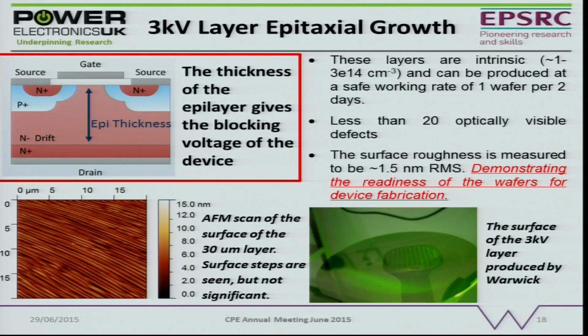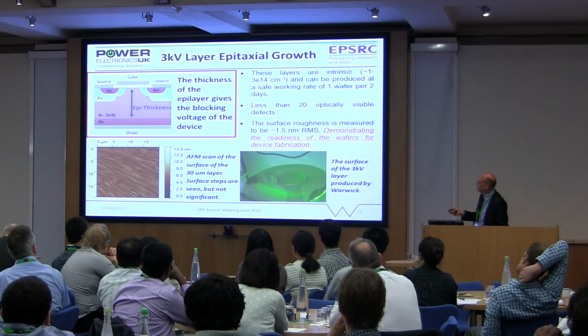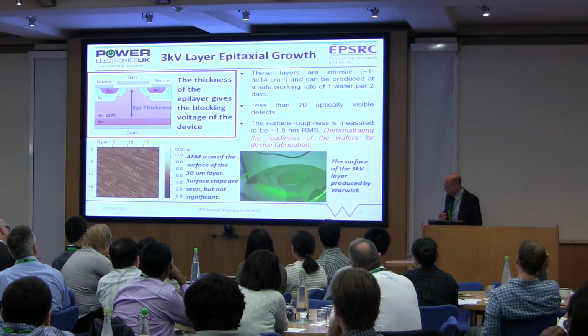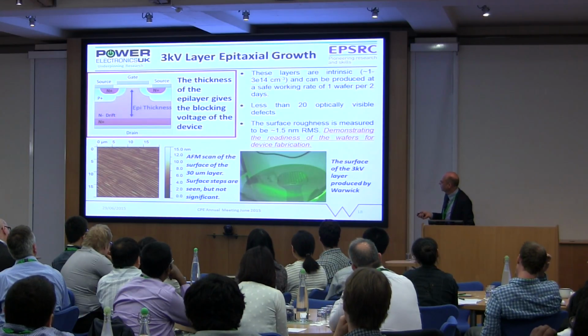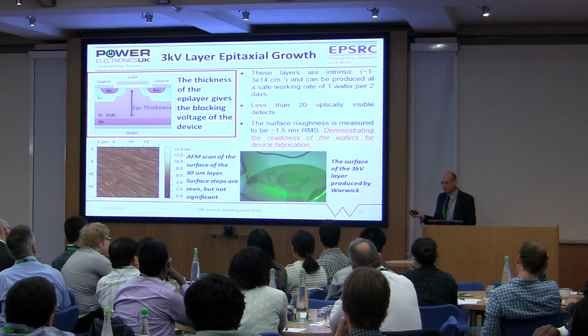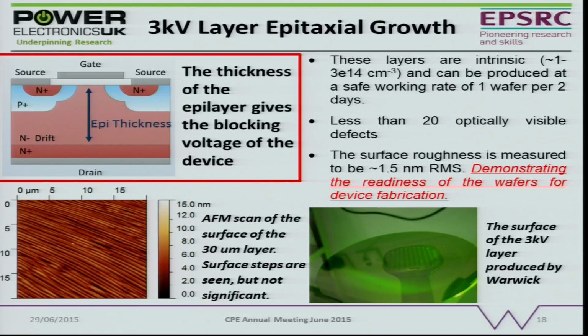So here's some of the work that's been going on in this work package. Obviously, we want to grow thick epitaxial layers. Typically, to get to 3,000 volts, you need 30 microns, and to get to 10,000 volts, you need approximately 100 microns of epitaxy. And the problem is, when you grow those very thick layers, you don't just grow it on the wafer itself. You grow it all over the equipment, the chamber that's being used to grow it in. So it's very expensive because you have to clean out the chamber very frequently when you grow these thick layers.